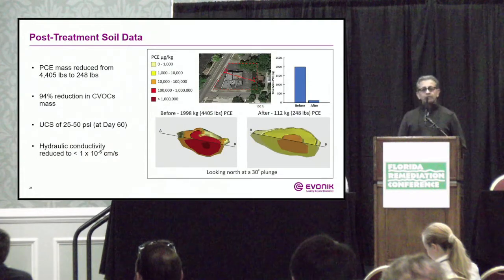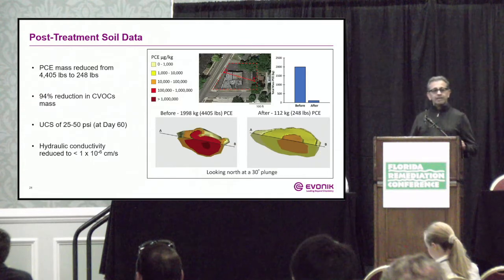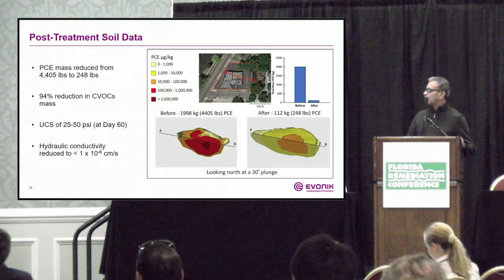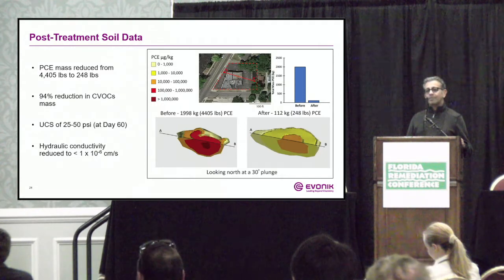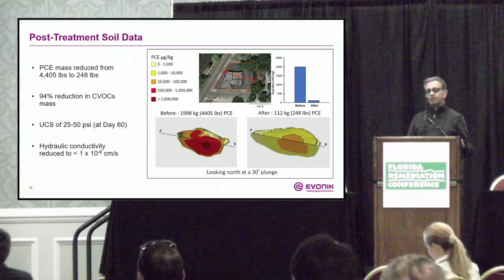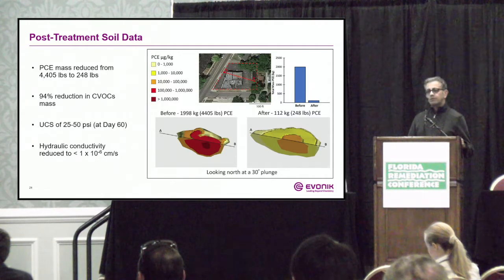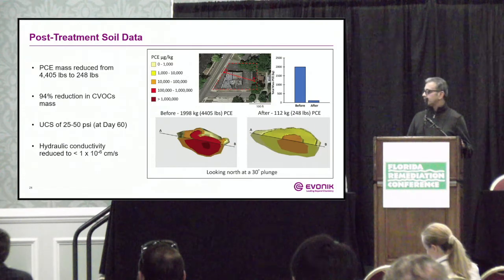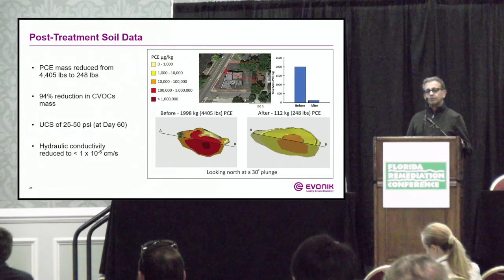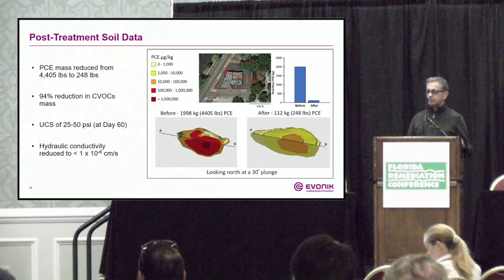An attempt was made to calculate how much mass was destroyed by using the soil samples and taking cross sections. The total PCE mass was reduced from about 4,400 pounds to 248 pounds. That was estimated at about a 94% reduction in the total CVOC mass. The UCS, the unconfined compressive strength, ranged from 25 to 50 PSI after 60 days, and the hydraulic conductivity was reduced to less than 10 to the minus 6 centimeters per second.